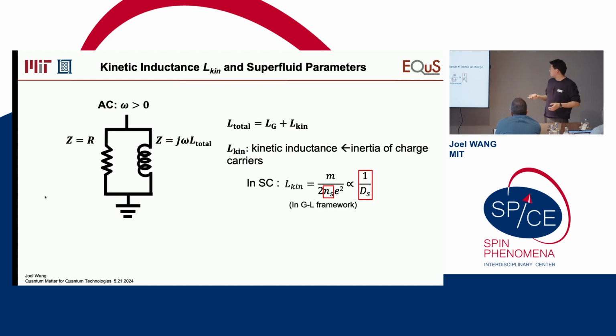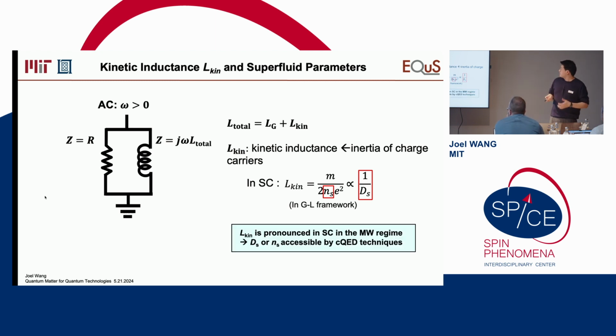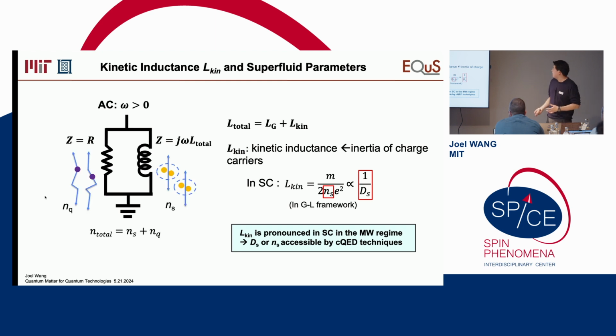So in the superconductor, it can be expressed as a function of the effective mass, and NS is the superfluid density, or the density of Cooper pairs, and it's also inversely proportional to the superfluid weight, or superfluid stiffness. So the kinetic inductance is actually pronounced in the superconductor in the microwave regime. So we want to use this advantage to study this material so that the NS can be accessible by the circuit QED technique that we just talked about.